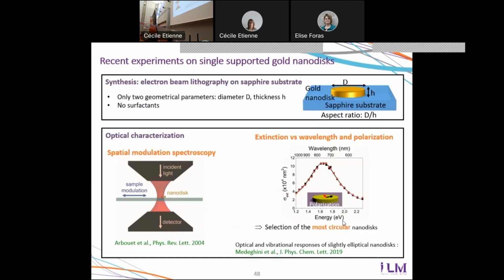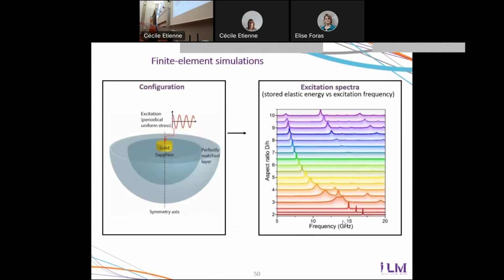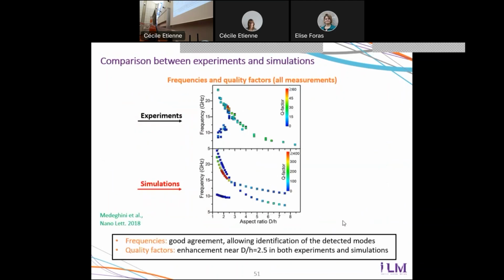It's something that we investigate complementarily with numerical simulations, in which we include the gold nanodisk and the substrate on which it is supported. Our simulation allows us to simulate the vibrational spectra of the object. So you see multiple peaks, which each correspond to vibrational modes, from which we can estimate frequency and quality factors. We compare with simulations, we see a very good agreement in terms of the detected frequencies. And the most interesting feature is here.